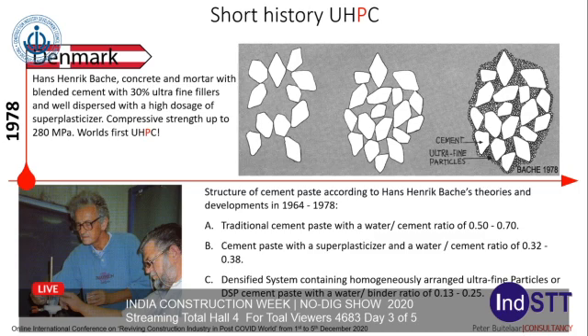Since it was possible in 1978 to disperse very fine cement, Bache experimented again with a blend of cement to reduce the pore size between the cement particles. After contact with a Norwegian colleague, Bache started to use microsilica and reached the ultra-high strength of 280 megapascal in his first samples. The use of the very fine spherical microsilica to fill the spaces between the densely packed angular cement particles resulted in a very low water-binder ratio of 0.13 to 0.25. This technology has been patented, which explains why later developments started after the 1990s.